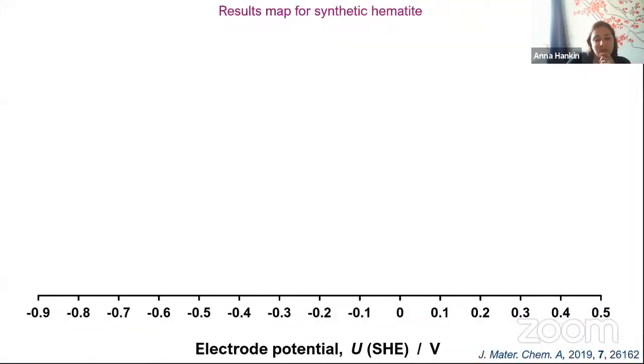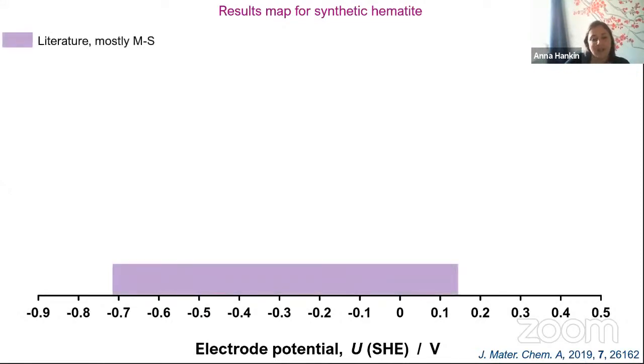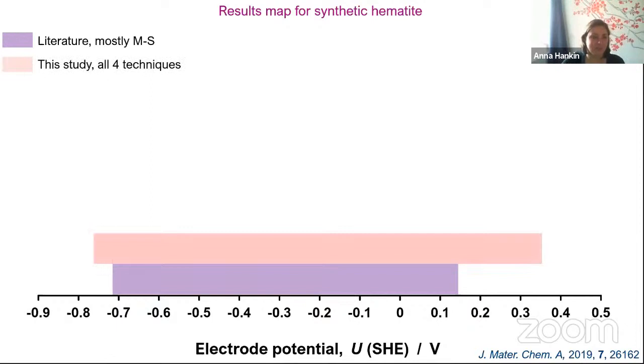And what I wanted to show, I'm not going to go into the details of the study because I could talk about it for hours to do it properly, but just to show the extent of the problem. So let's say this axis here is the electrode potential. So that more or less spans your 1.23 volts required for water splitting. If you look into the literature of the results for synthetic hematite that have been reported, and this is a lot of publications, this is the spread. So more than 0.8 of a volt spread in what's supposed to be a very precise value used in modeling. So then the study that I did using all four different techniques gave an even bigger spread.